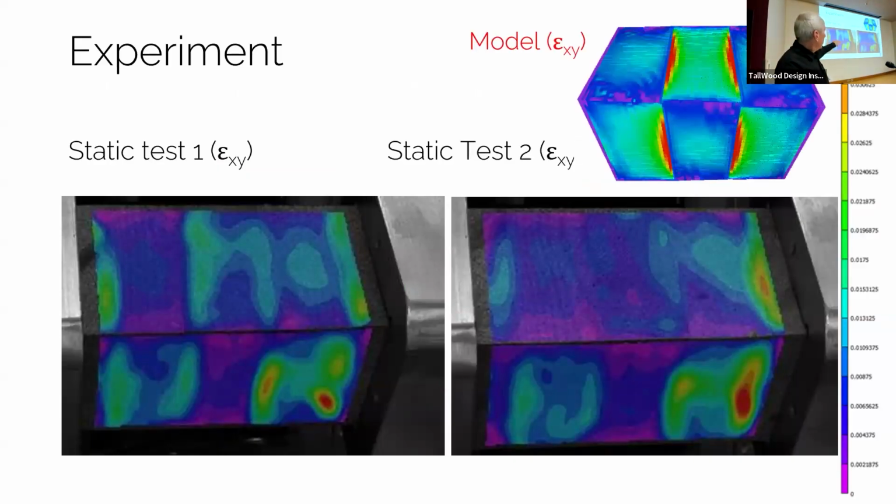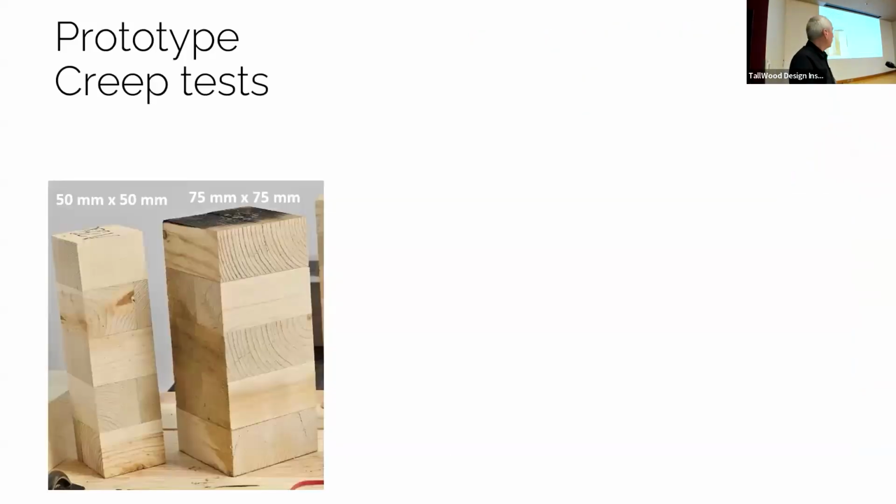So now if we look at the surface, this would be the outcome of this modeling that we've done before, but just the strains on the surface. And this is what we measure. I think we are pretty close. This gives us some confidence that we actually can translate what we see in terms just of an angle to the stress and strain state inside the samples and make a little more educated statements about it. This is how our specimens look like.